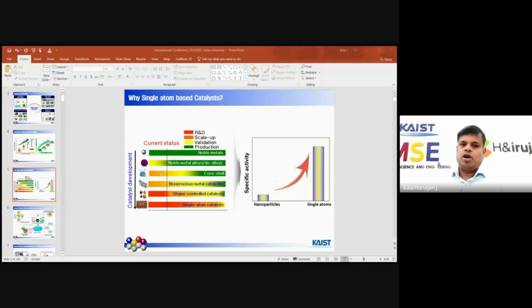Before they go from noble to non-precious materials, they go for noble metal mixed with non-noble metals, to reduce the amount of noble metals. After that they make core-shell materials. What is the advantage of the core shell? The core shell may prevent the active material from degradation, and non-precious materials especially give high performance, but even so there is still no certification for the noble metal amount, like a noble metal standard. Therefore people go for shape-controlled materials, and finally they go for single-atom based catalysts.